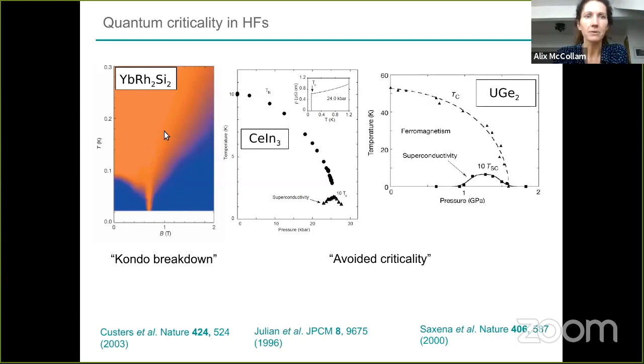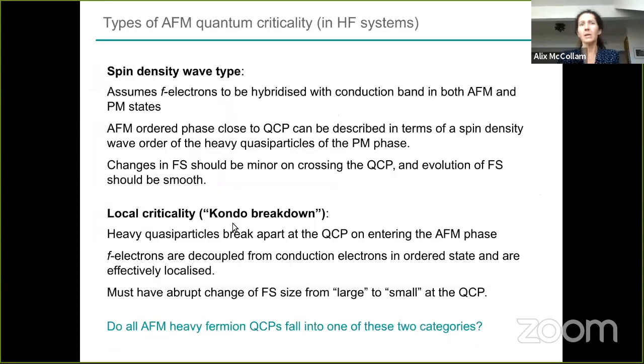So this again is the famous ytterbium rhodium 2 silicon 2 phase diagram, and the quantum phase transition here as a function of magnetic field. This is cerium indium 3, again, a very famous phase diagram that everybody is probably familiar with, and uranium germanium 2. So this is a ferromagnetic system. I'm going to talk about antiferromagnetism, and primarily about field tuning, although not about ytterbium rhodium 2 silicon 2. So in heavy fermion systems, you could say that there are at least 2 types of quantum phase transition. So this is a zero temperature phase transition tuned either with pressure or field or with some other chemical doping, some other tuning parameter.